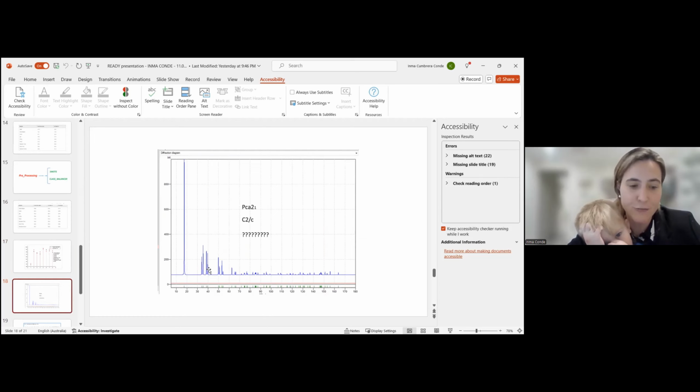So for validation, we propose a challenge to validate our methodology: a diffraction spectrum corresponding to tantalum doped zirconium oxide, which corresponds to a completely unknown structure. By physical algorithms themselves, it was possible to assign the Bravais lattice with two possibilities. The first corresponds to a primitive orthorhombic lattice, which was class number 6, or to a monoclinic centered in the bases. Finally, it could be known by physical methods that the validated solution was the one above, primitive orthorhombic. The only way to break the ambiguity was that the material was piezoelectric and ferroelectric, which is incompatible with the second type of Bravais lattice.